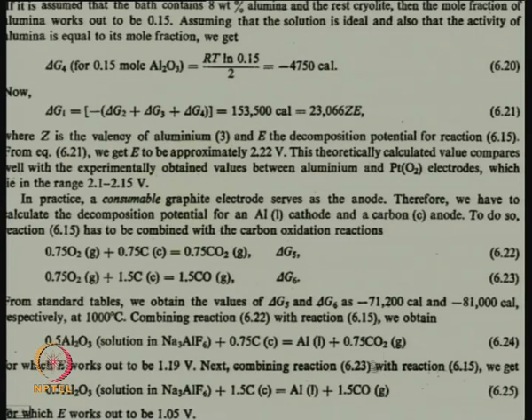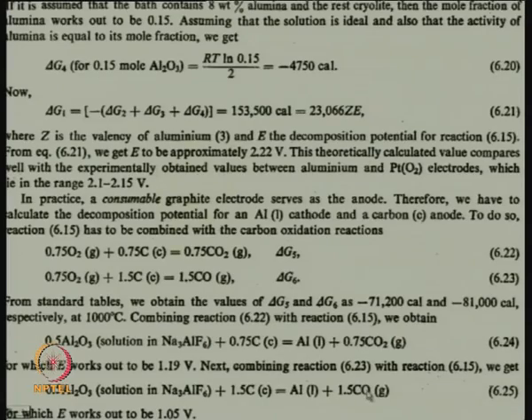For this, our decomposition potential would be 1.19 volt, which means carbon coming into the picture, eating away oxygen, has made the decomposition easier. Had it been only aluminum and oxygen, there was a certain voltage, but this oxygen is now consumed by carbon. So, the dissociation is made easier. So, the voltage is almost made half. If it is forming CO, which is more likely because you are operating at 1000 degrees where there is more CO than CO2, it is even lower, 1.05.